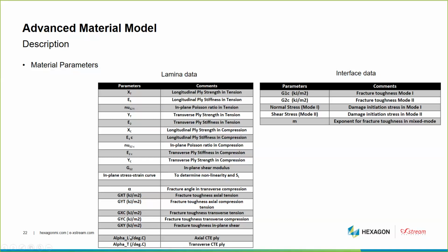We need also the coefficient of thermal expansion of the ply, so the axial and the transverse. So this is to take into account the residual stress coming from the manufacturing. And then we need also the interface data. So interface data is the fracture toughness in mode 1, in mode 2, and the nominal or damage initiation stress in mode 1 and in mode 2.